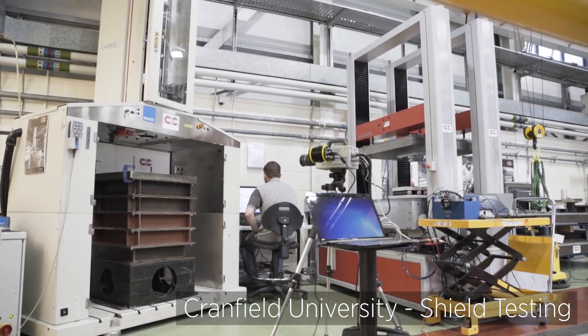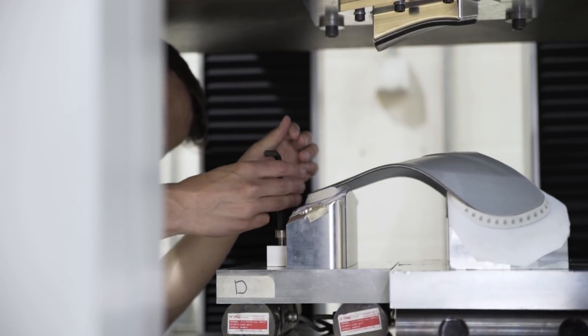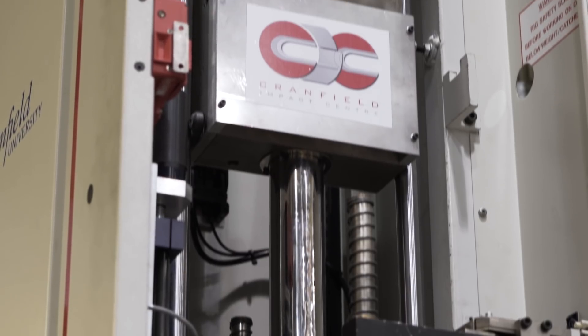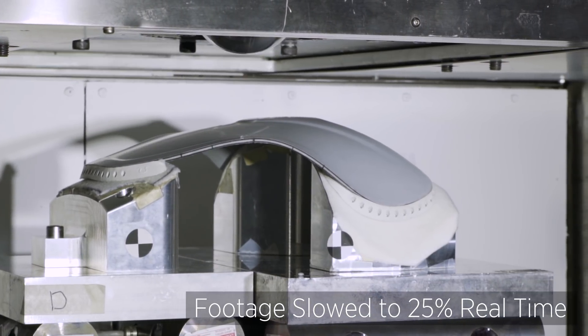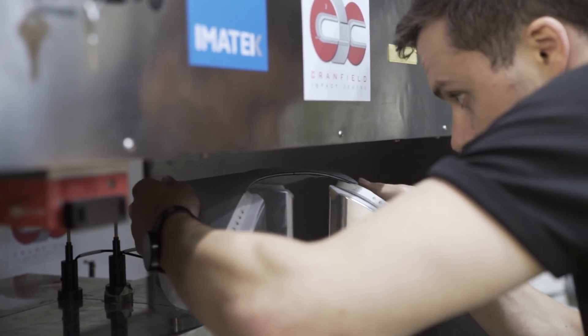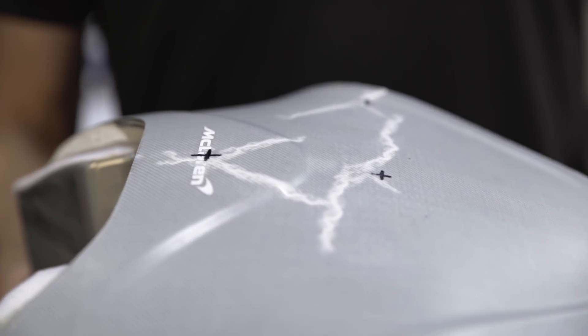To inform the design of the shield, we predicted a series of impact events that the shield was likely to be exposed to. These were based on insight into the client's lifestyle wishes as well as the design standards of motorbike armour. Prototypes of the shield were put through a demanding test programme, carried out at the same facility used for the crash testing of Formula 1 chassis. A drop tower was used to apply a variety of impacts to the shield — one example being the equivalent of dropping a bowling ball onto your foot from waist height, which the shield successfully passed.